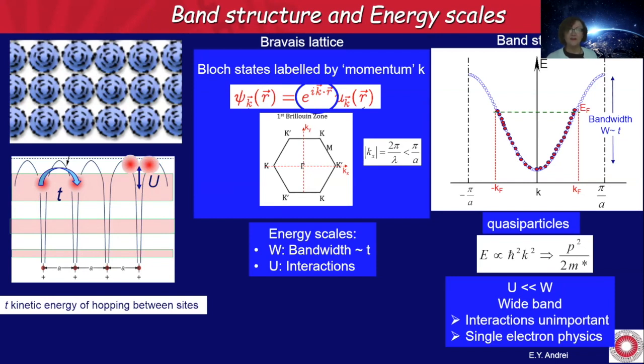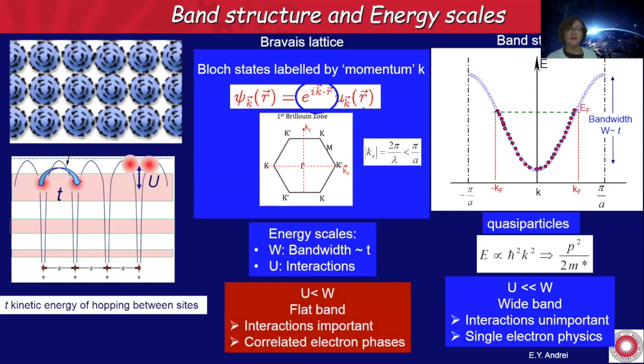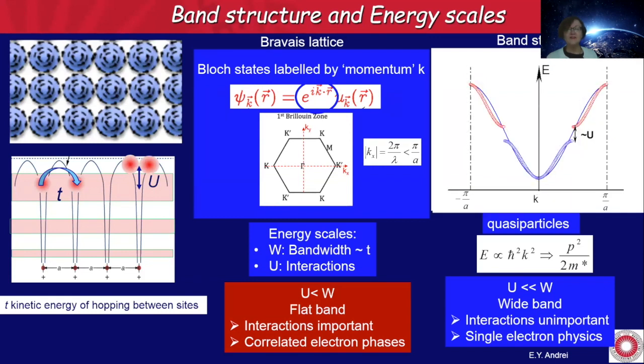In the other limit, where the interaction energy is much larger than the bandwidth, sorry, this should be a larger here, what we get is a quenched kinetic energy, and the electrons can band together and form a correlated state that is macroscopic and where all the electrons move in step. And the band structure changes here. You open a gap. And this, for example, can be a superconducting state or other kind of correlated state.